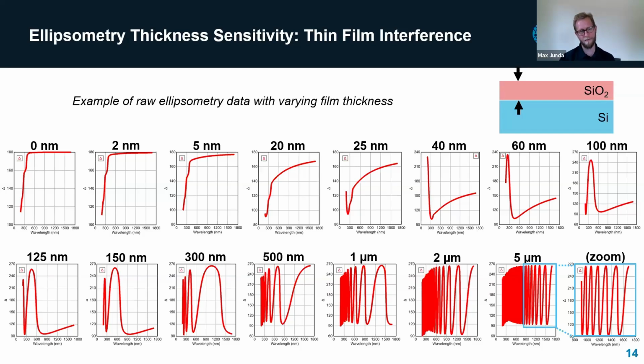And then right next to that, you see we have a 2 nanometer silicon dioxide film. And if you noticed, the raw data is almost exactly the same. Looks very similar, but you can see it's just tweaked down a little bit. It's just adjusted slightly from the case where there's no film. And that's basically what we're measuring in the case of very thin films. It's just little offsets in the data. And then we keep going to 5 nanometers, 20 nanometers, 25, on and on.